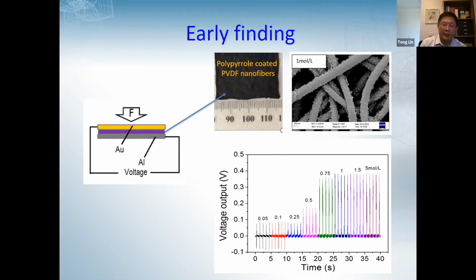Then we conducted a series of investigations to find out what happened in this device. Eventually we found it comes from two reasons. One is the use of the conducting polymer PPy. Another is that we mistakenly used two different metals as electrodes to form the device. One electrode was gold, the other aluminum. But the nanofiber may not be necessary for this energy conversion. So we came back to understand what happens if we just use the conducting polymer and two metals.